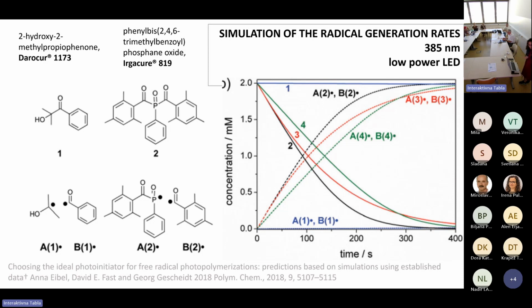So, researchers at the Institute of Physical and Theoretical Chemistry in Graz have prepared simulations of radical generation rates. And this graph represents this simulation. And as we can see, the blue line is for Darocur 1173 under this low-powered LED. This initiator didn't decompose and form radicals, but the Irgacure 819 did decompose and form radicals, and the speed of formation of radicals is rather fast, especially in comparison with thermal initiators. So in this case, we can speak about seconds to form radicals.